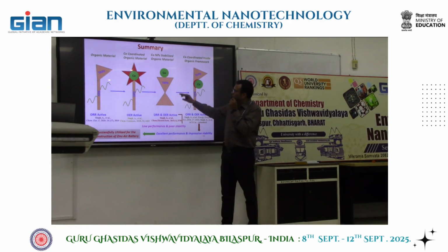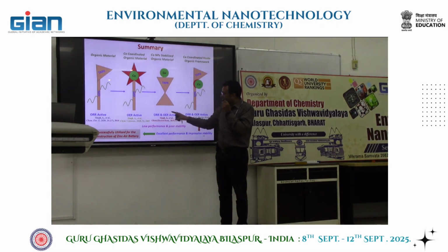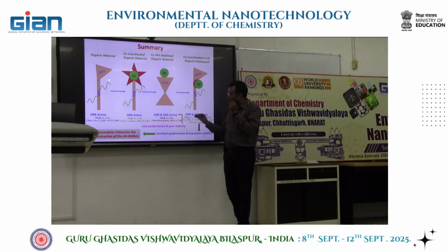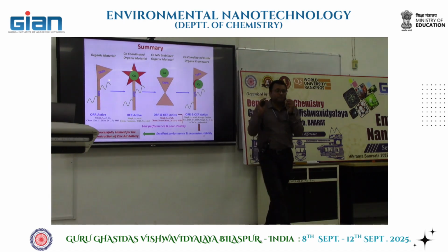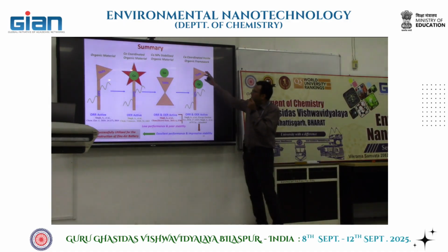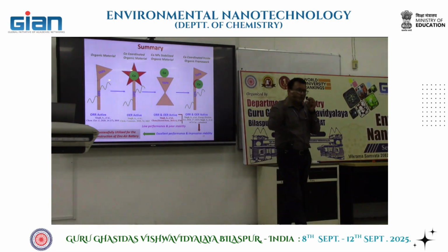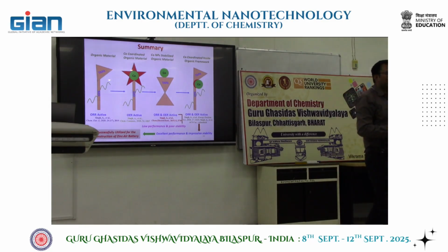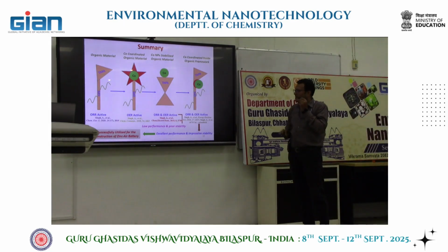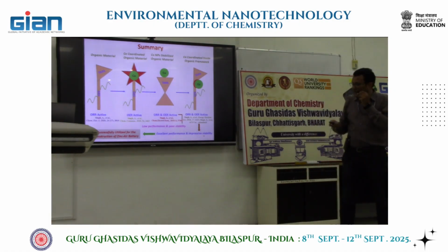And the third one, where we have both the properties, TPA (triphenylamine) and cobalt, but as a nanoparticle, was active for ORR and OER but had low performance as well as poor stability. But in the fourth design, where triphenylamine and cobalt are integrated in a coordinated, atomic form in the framework, that showed excellent performance and nice stability towards the zinc air battery, and we have successfully constructed that.